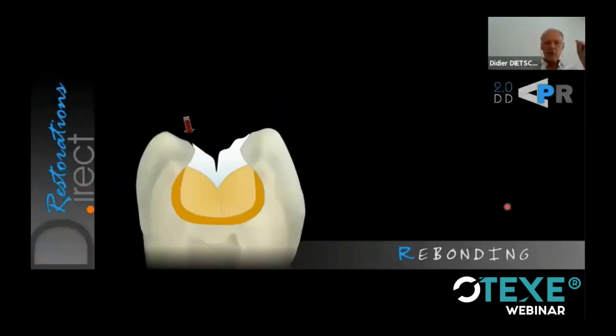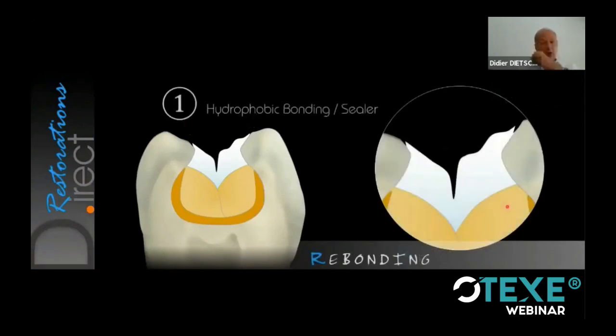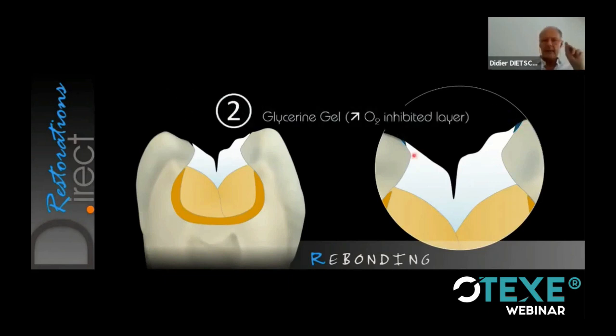So the rationale of the rebonding is to make the margins perfect, because those micro defects, they are of course exaggerated here. On my drawings, they are never as big as that. But if you go under the scanning electron microscope, you will see those little cracks, those little defects. Those defects could be just at the margin, could be sometimes also inside the enamel. You might have micro cracks into the enamel. So what we do with the rebonding, we seal those margins, and then we cover everything with the glycerin, and we light cure.